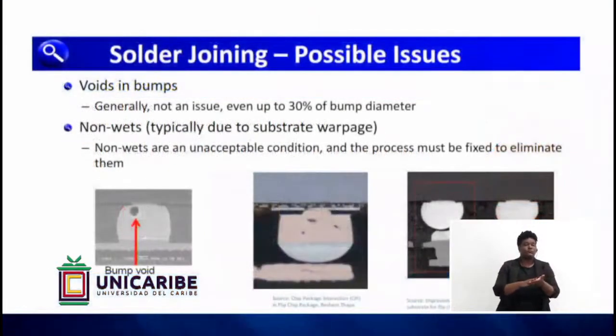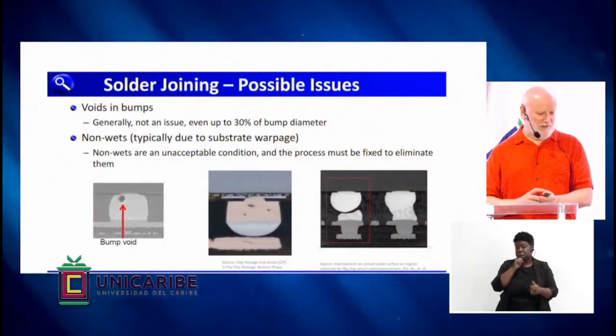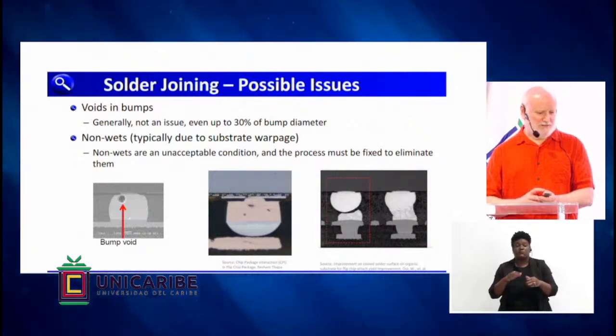This is just showing some of the possible issues that can arise in bumping. You see some voids there. Interestingly, voids generally are not a problem. You could have even as much as 30% void in a bump and in a solder connection, and it's almost never a problem. But the ones on the right are real problems. These are non-wets where the joint was never properly formed between the two sides.